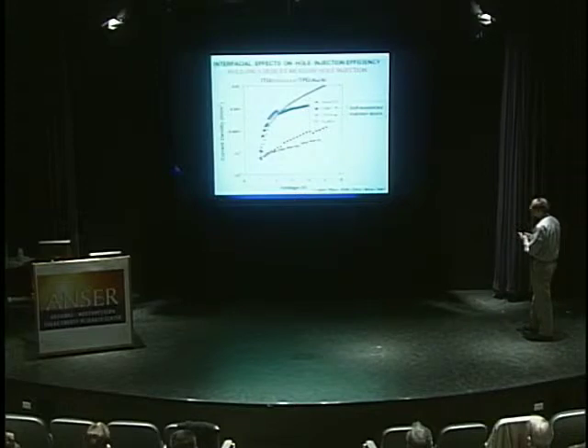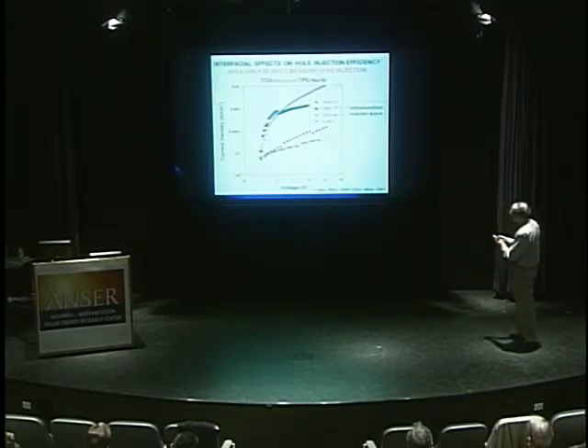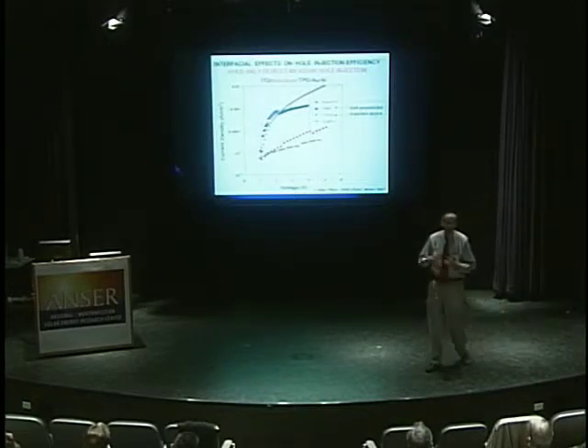Now you can do some physics. This is called a hole-only device. So we're going to compare devices where it looks a little bit like an OLED, but there's a layer of gold there, and that blocks electron injection. So all you measure, it's called a hole-only device, is hole injection across this interlayer, and then we varied the material in this interlayer. And so this is copper phthalocyanine, and this is the current density. This is bare ITO, and then these are 2 different organic self-assembled injection adhesion layers that we synthesized. You can see a tremendous increase in the flux of holes flowing across this interface.